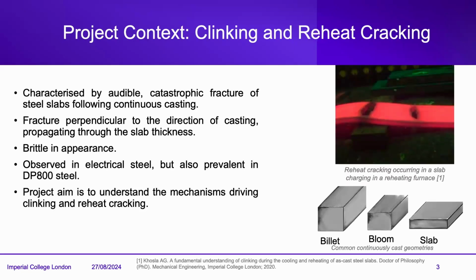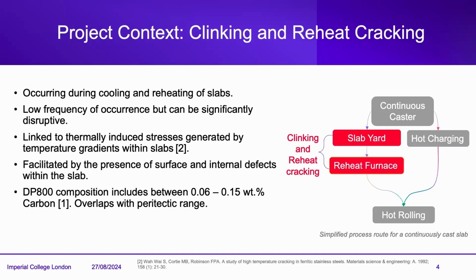To begin with, the reason why observing the fracture toughness properties of as-cast DP800 is important in this case is due to the phenomena of clinking and reheat cracking. These phenomena are characterized by brittle, audible fracture of steel slabs after they have been continuously cast. This fracture occurs perpendicular to the direction of casting and propagates through the thickness of the slab. The aim of my project is to further an understanding of these mechanisms that result in clinking and reheat cracking. As I mentioned, the phenomenon happens after continuous casting.